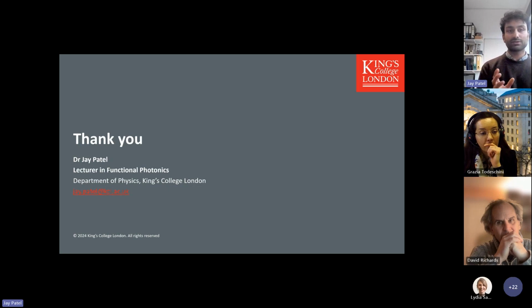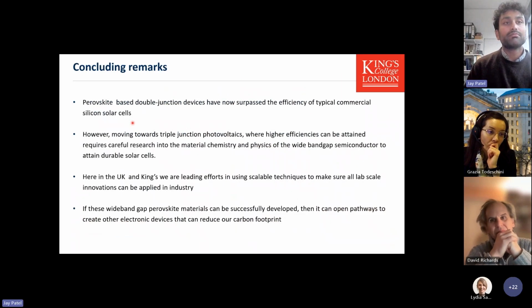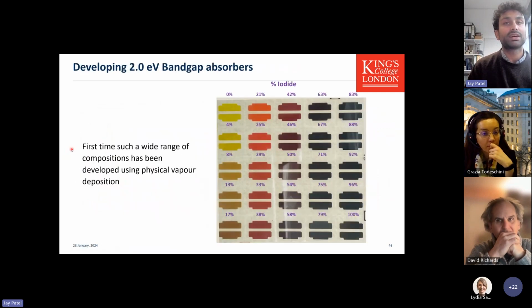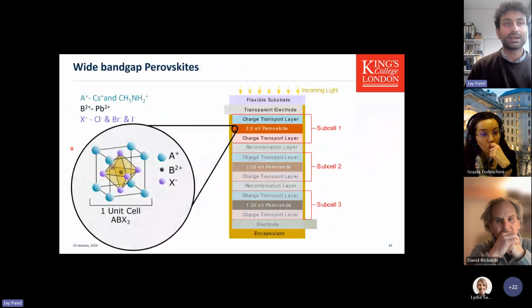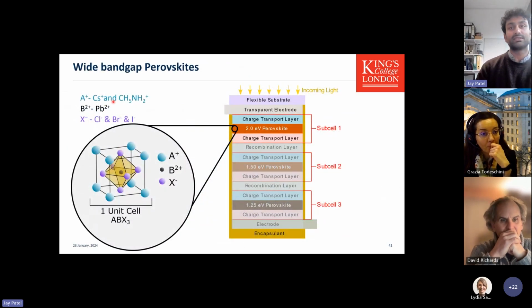For example, I showed that the crystal structure is adept at, I can just show you the slide. The crystal structure you can change such that, hold on. Okay, so the crystal structure here, you can actually change these A-site cations into phenyl groups or aromatic rings, which are hydrophobic. So essentially, if you cover that top layer of a material with a hydrophobic A-site cation, then the material becomes much more stable. There are all these routes that we're trying to implement to make the material more stable in the environment. But in terms of recyclability, these are all readily soluble in solvents, and sadly also readily soluble in water. So that's the double-edged sword, I guess.